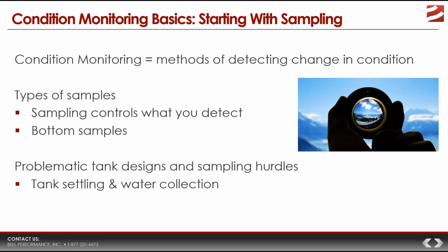So what are some of the hurdles here with sampling? Well, you can be hindered by the design of the tank in your sampling. What is the one thing that goes most hand in hand with microbial content in stored fuel? Well, that would be water content, of course. That means if you're doing condition monitoring and trying to detect possible microbial presence, by necessity, you are also going to be looking for the presence of either free or emulsified water content. Yet, it's not uncommon to have a storage tank that has zero detectable free water if you're measuring at the fill end. And yet if you were to go to the turbine end and do a measurement, you would find 50 gallons, 100 gallons of water sitting down there waiting to be pulled off if you actually knew it was there.